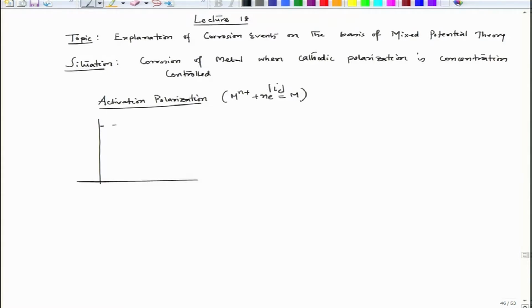this is E equilibrium of the cathodic reaction, this is I 0 of the cathodic reaction on the metal surface. So, here we are considering the same cathodic reaction. I could say that instead of C I can write M.